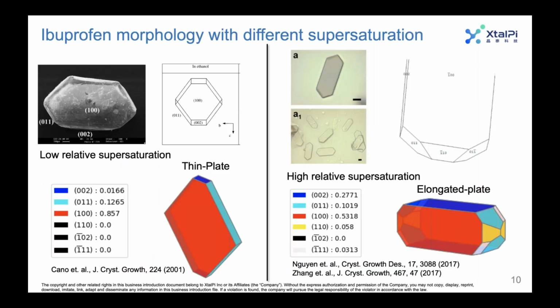Another example using ibuprofen is to show you the effect of supersaturation and how that can be modeled. The image on the left was obtained at relatively low supersaturation, but when you crystallize ibuprofen at a higher supersaturation, you actually get a change in the morphology. Specifically, you get some elongation about the 002 face. You also see the appearance of this 110 face on the tip of this needle.